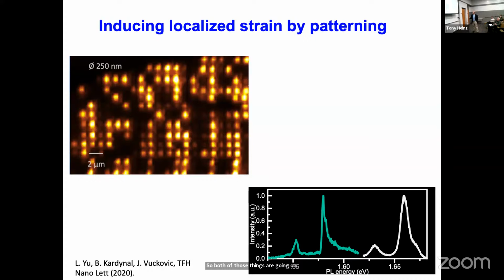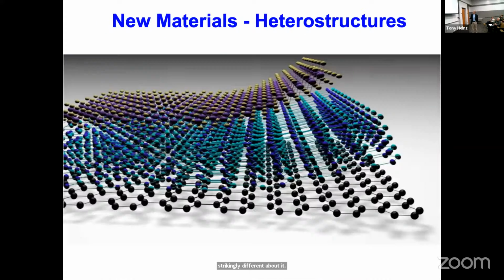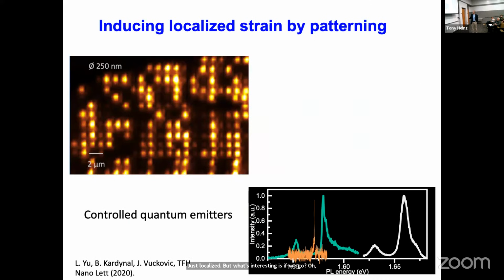If we look at the corresponding emission spectra, this is from the region of the sample away from the holes, and this is in the holes. So we've shifted the emission by a significant amount. Otherwise, in this case, it looks fairly similar. It's a sort of a shifted version of this. This turns out to be one of those tunable features that I talked about before. So we can pattern the behavior, but you would say in this regime, there's nothing strikingly different about it, just localized. But what's interesting is if we go to a much smaller lateral dimension and we look at the emission spectrum, it starts looking really different.